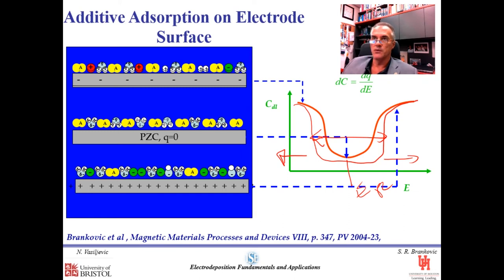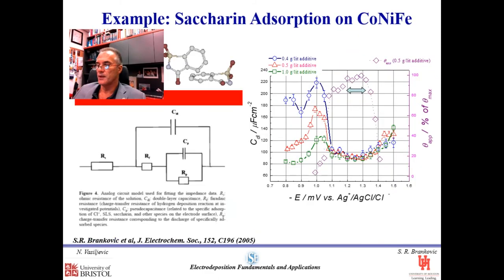So, if we are really looking into using certain molecules as additives, we have to have a good idea where the PZC of the metal is which we're trying to deposit, and whether these molecules actually do adsorb significantly on the surface in this region. And if they do, we should run the electrodeposition process in such a way that the electrode potential during the deposition process is in this range where the additive does adsorb.